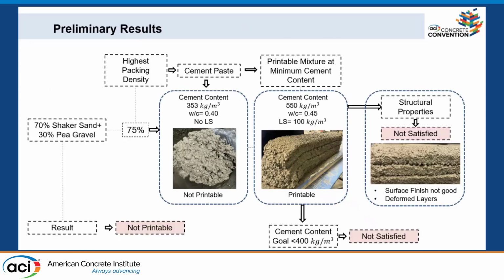Now we have tested our packing design, we have tested the mixture, and for the first one we have tested the highest packing for the shaker sand and the pea gravel. Here the packing density was 75%, so the void content was around 25%. We tried the cement paste, but the cement content was lower. It was 353 kg per cubic meter, but the mixture was not printable. So we found a way to make it printable, but the cement content for the printing was not successfully covering our cement content goal. That was lowering the amount of cement which is below 400 kg per cubic meter.